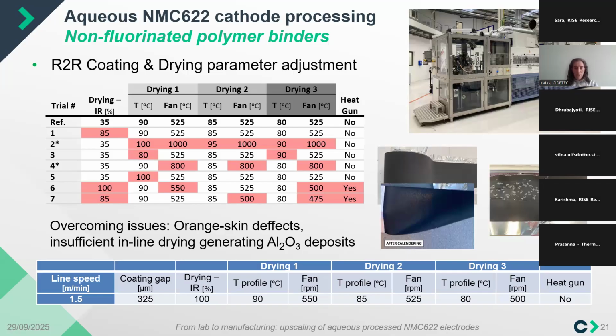So what we have found is that it's necessary to reach at least below 5% residual or relative humidity, which you can measure with some simple sensors, in the electrodes at the end of the drying before going to the post-drying step, to avoid having further reactions while the electrode is being post-dried.